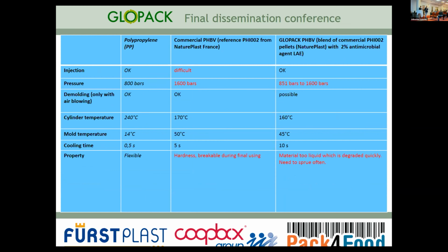We tested a compound with 2% of antimicrobial agent, but the material was too liquid, and we obtained not good processability, with variation of the pressure, because the material is degraded quickly inside the cylinder. So it's not representative of a normal injection, but we obtained cups for analysis.